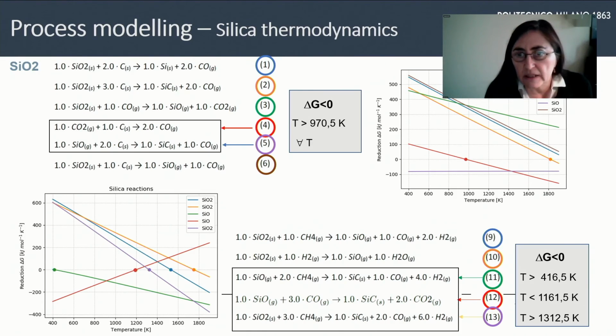And at the very end, we identified, at least from the thermodynamics point of view, a reason for having the reaction occurring, even if we are not melting the silicon components. And this is because there is a path for creating silicon gaseous components that allows the reaction with methane happening at a much lower temperature.